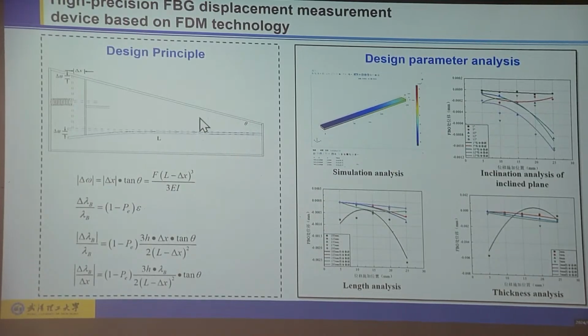For large deformations, you need to measure the strain. Normally, if there is a large deformation, the fiber Bragg sensors cannot be extended for high or large strain. So we developed this device to convert the large deformation to small strain and deformation, because we convert this deformation into the bending moment of this beam. So you can understand the deformation of the beam related to the displacement of the device.